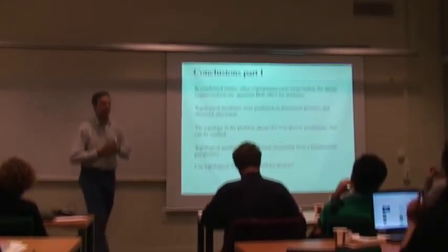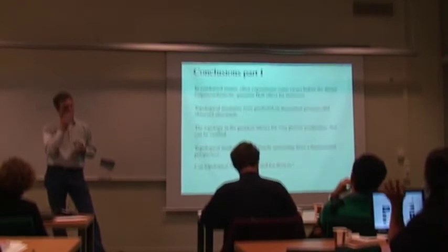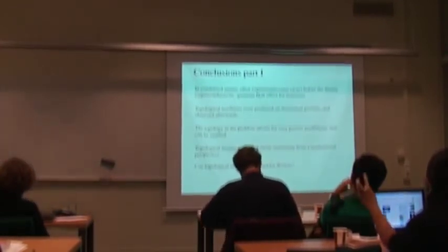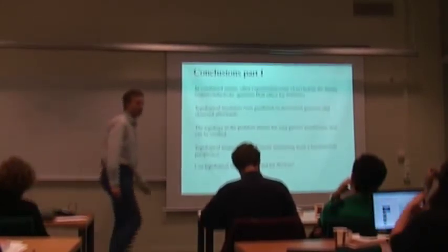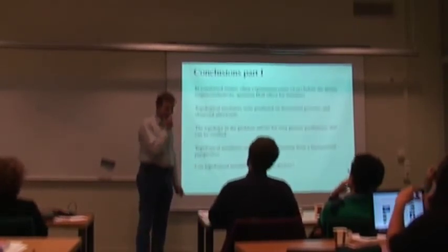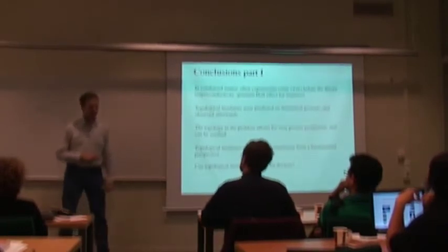Two quick questions. You talked about graphene. Was it surprising that the case was only trivial? Because we're only talking about the special edge states in graphene. So no, it was actually expected. And that has to do with these cadmium telluride, mercury telluride. They're really heavy atoms, and they give rise to very strong spin-orbit coupling, which is actually necessary here. And carbon has very weak spin-orbit coupling. So that's the answer.